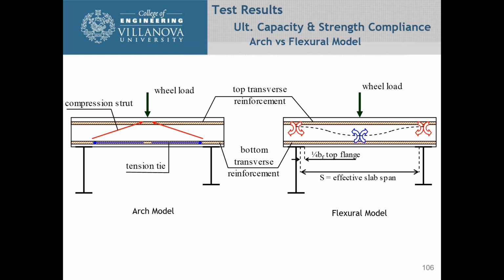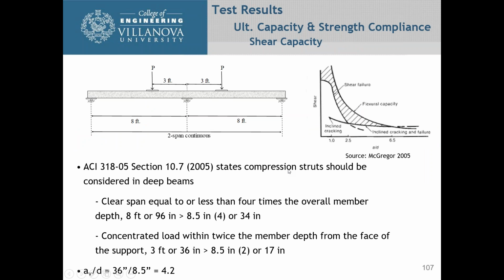So what that's kind of telling us is that for the GFRP, the failure mode was more the tension strut that we see on the left. And it wasn't necessarily a shear failure in the terms that we are thinking of. You're creating a model here with a load coming down, and you had the GFRP bars acting as a tension rod, and then you had a compressive strut being formed. For the flexural model, it was more what we look at for our traditional design.